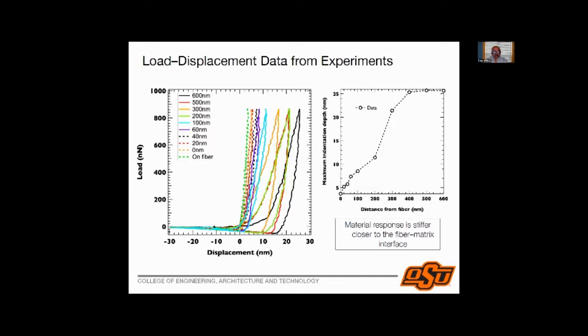But right now, if you look at this black curve, the black curve is much less stiff than the curves that are closer to the fiber. So what I'm seeing over here is, I have my carbon fiber. I carry out my indentation. If I'm far from the carbon fiber, then the indentation response is very soft. If I'm right next to the carbon fiber, then the indentation response is very stiff.